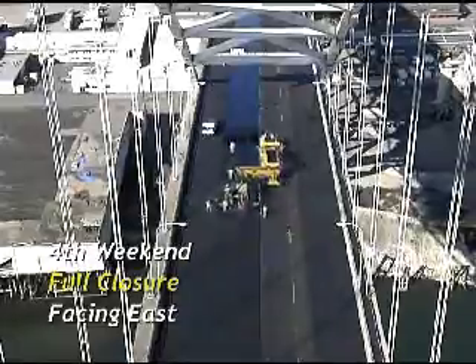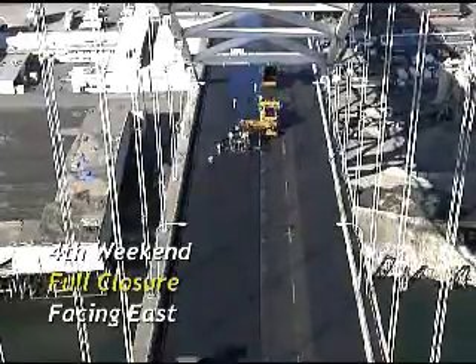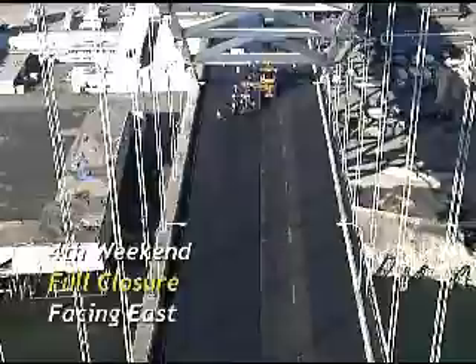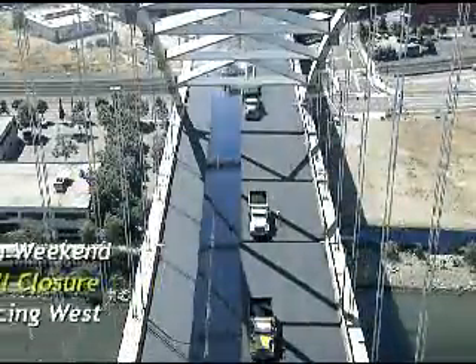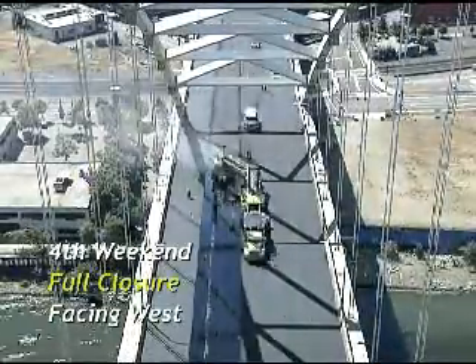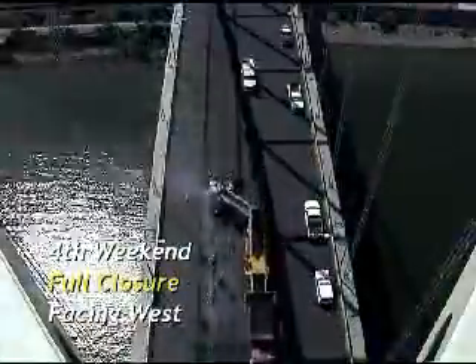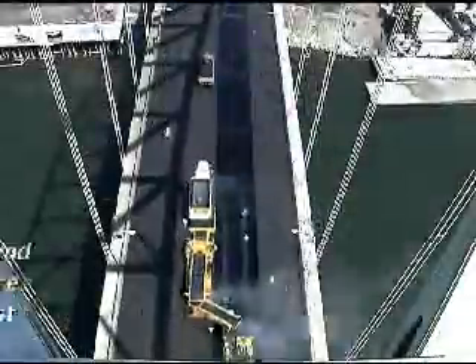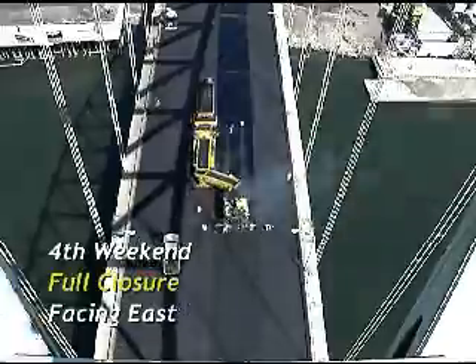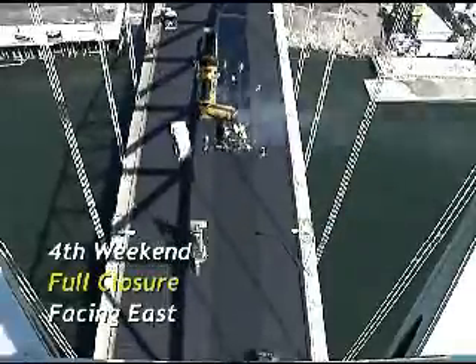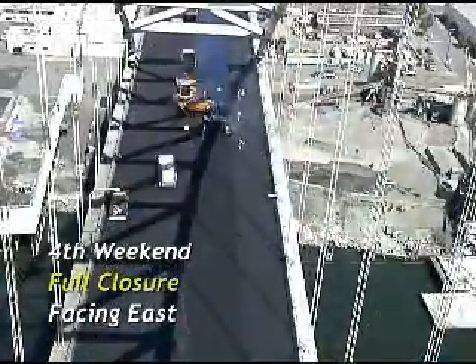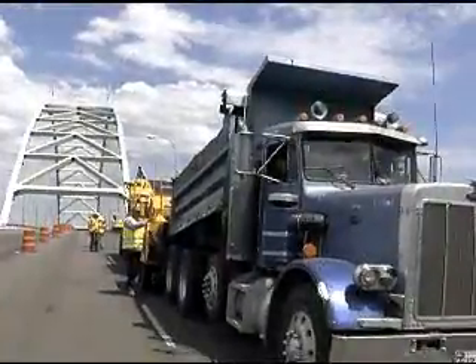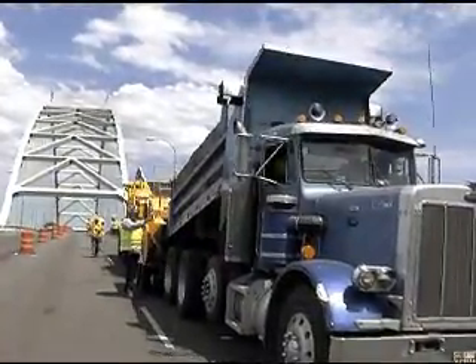Each truckload is about 12 tons of asphalt. The asphalt's made in batches, and each truckload holds about 3 batches of asphalt. And to go along with other requirements we have for the contractor to produce the mix, they've got to make those 3 batches within 7 minutes. If it takes longer than that, there would be too much variability in that truckload, so we would have to also reject that load and throw it away.